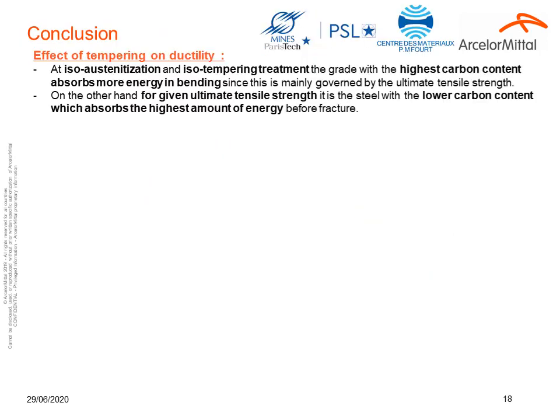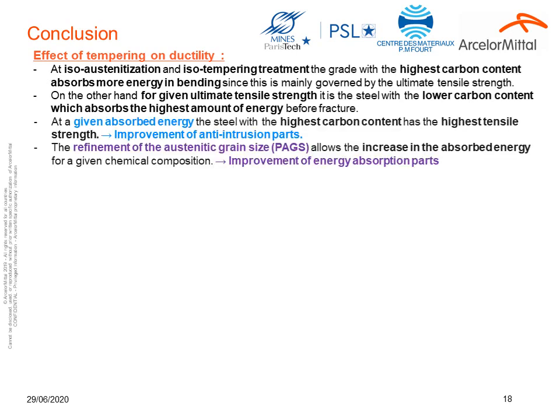In conclusion on the effect of tempering on ductility, at iso-austenitization and iso-tempering treatment, the grade with the highest carbon content absorbs more energy in bending, since this is mainly governed by the ultimate tensile strength. On the other hand, for a given ultimate tensile strength, it is the steel with the lowest carbon content which absorbs the highest amount of energy before fracture. If you place yourself at a given absorbed energy, the steel with the highest carbon content has the higher tensile strength. This could be a way of improvement for anti-intrusion parts.